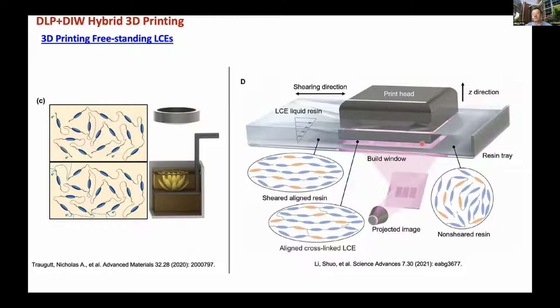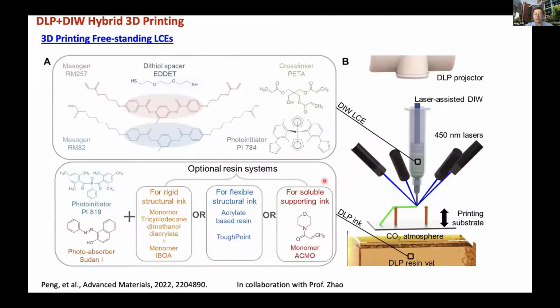That's before Carbon, the DLP printing essentially, and they try to separate the printed layer from the substrate to do the shear. So they're actually using this shearing approach to align the LCE. But still, in this case, your LCE can only actuate in one direction. So I challenged my student Xirui Peng, who just defended his thesis. We asked him, can we do printing in the air, right? So just to do a freestanding printing.